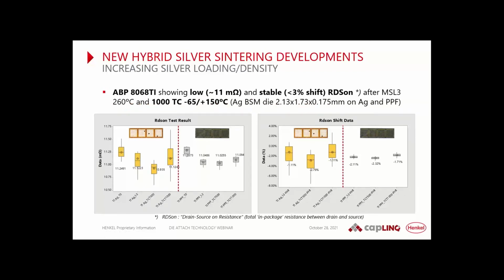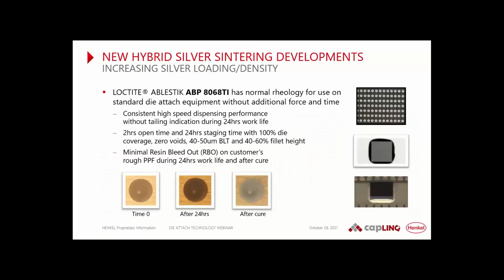Nevertheless, this material got qualified in certain applications, power applications, and especially showing very low and very stable RDS on after reliability testing. And that's the reason why it got qualified and starting in production. And for the rest, also here, same easy dispensing, just like a normal die attach, and typical work life of 24 hours. Basically the way of working of a standard die attach dispense process.